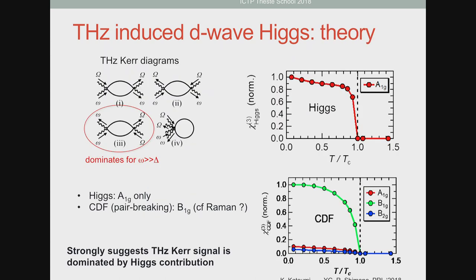Now, you can actually look at diagrams to explain this third-order nonlinear response. They are essentially Raman-like diagrams, but there are more. So for example, in Raman-like diagrams, you would have this kind of diagrams. But when you do pump and probe, you can have such diagrams, for example, where small omega is the optical probe and capital omega is the optical pump. And actually, in the non-resonant regime, this is the kind of diagrams that dominates. And you can compute the contribution of this diagram both to the pair breaking channel and to the Higgs channel. And what you can see is that generically, again, the Higgs mode will only appear in the A1G channel.